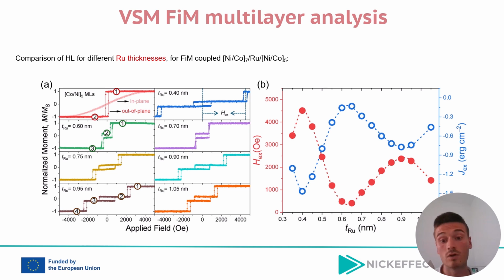With respect to panel B, this quantifies this behavior by plotting the exchange field and the resulting exchange energy versus the ruthenium thickness, which both exhibit, as expected, oscillatory behavior, characteristic of these RKKY-type interactions. Overall, this data emphasizes the critical role of the ruthenium spacer thickness in tuning the magnetic coupling.